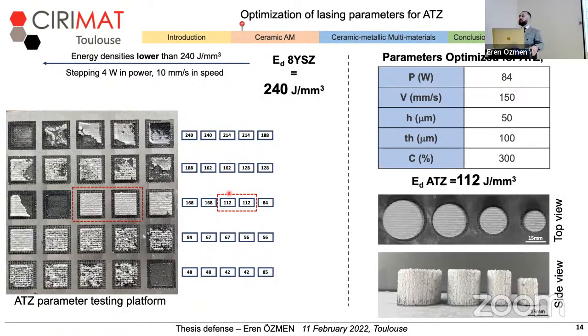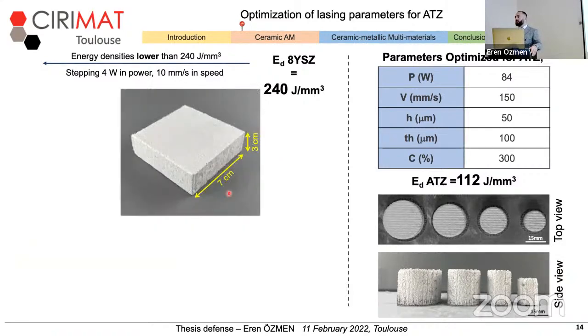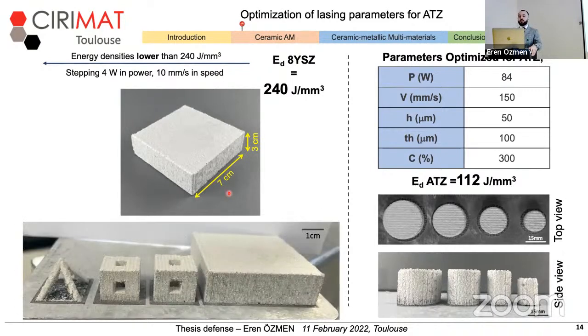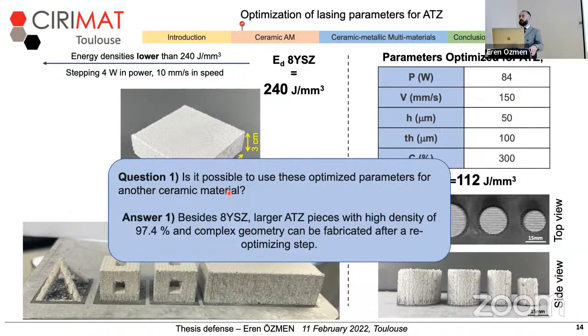And when I go for upper limits, ATZ pieces larger in surface area and higher in the Z direction than 8YSZ were possible to fabricate. When we go to upper limitations, very big solid pieces were possible to fabricate, and also complex shapes with inner cavities and hanging structures were possible to fabricate as well. So we can answer the first question here: yes, with the re-optimization of lasing speed and lasing power, similar fabrication patterns can be used for a new material such as ATZ.